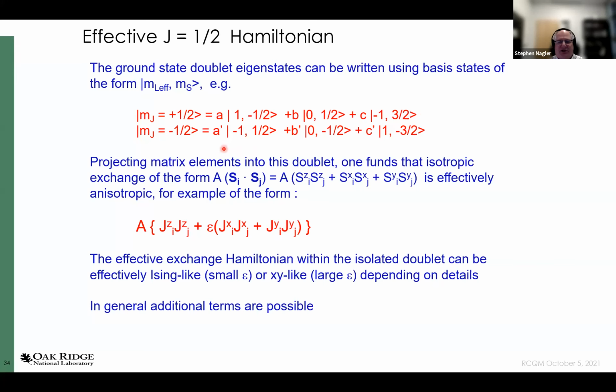And if I simply assume that there's a true Heisenberg coupling between the true spins, but I project it into this mixed spin orbital doublet, it turns out that within that doublet, the effective, if you like, exchange interaction is anisotropic, right? So I can generate Ising-like or XY-like exchange in this way. And of course, I can also get additional terms in the Hamiltonian.